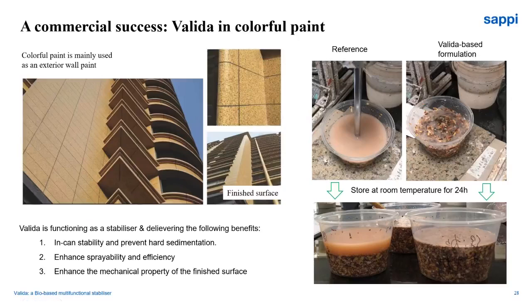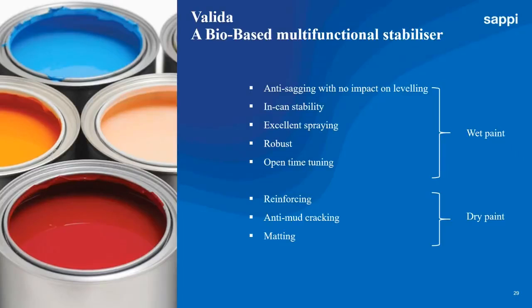Finally, to conclude, Valida is indeed one single additive. However, it brings multiple superior functionalities to waterborne coatings. In wet paint, it improves the in-can stability, improves the anti-sagging with no impact on leveling, and improves the sprayability. It is robust and is able to tune the open time. In terms of dry paint, Valida helps in achieving higher mechanical performance, helps in solving the mud crack issue, and also delivers a matting properties solution.